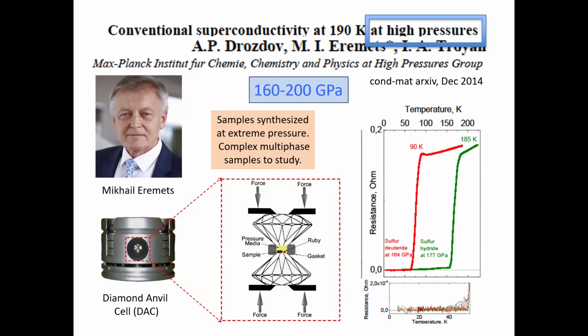And then replacing hydrogen with deuterium, which is still just one proton, but it has a neutron, so it's twice as heavy. And the vibrations are square root of 2 lower in energy. Then this follows the theory. There's this huge isotope effect in TC. This verified it's a superconductor, and this shift verified that it's being paired by the interaction with the vibration of the atoms in the crystal, and in particular, the hydrogen atoms here. And here's the demonstration of effectively zero resistance down here.